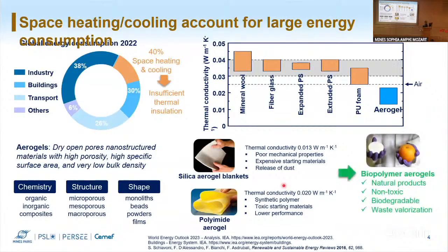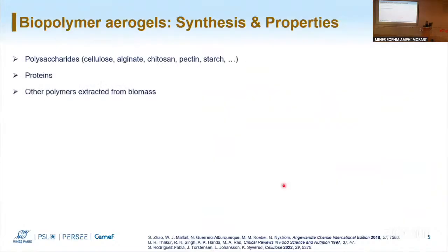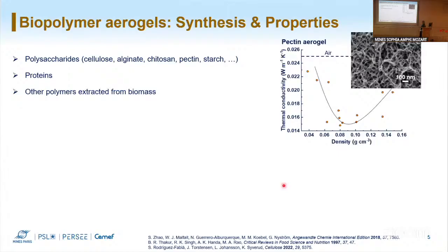What we want to do is to pass to biopolymer aerogels, so to have natural products that are non-toxic, biodegradable, and come from waste valorization. Let's see which are biopolymer aerogels. Usually they're from polysaccharides, protein, or other polymers coming from biomass. And from this family of materials, we know that pectin aerogels possess one of the best properties regarding thermal insulation. We can see here that for a range of formulation, we have super insulating properties, and we can reach down to 15 milliwatt per meter Kelvin, so much below air.